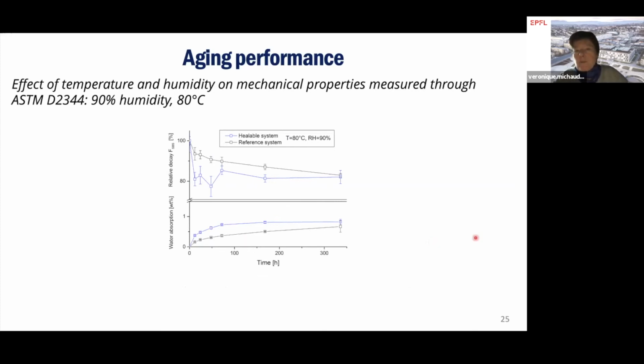Another thing that we looked at was the aging performance of this new matrix material. As compared to the reference system, by putting it at 80 degrees in a high relative humidity for several days, we saw that there is a water absorption that is a bit higher than what we would have for the reference epoxy, and a bit of decay in short beam strength after this exposure, but actually not so bad as compared to the epoxy system, so it was still acceptable.